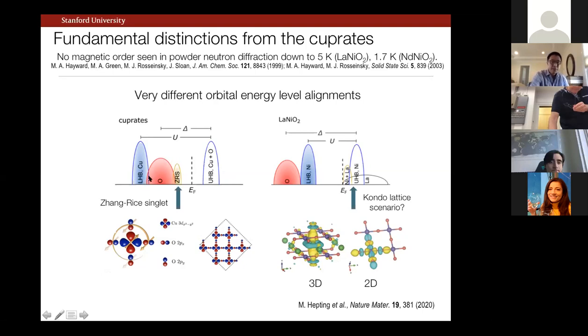The oxygen 2p band is lying around here, such that when you start to hole dope this system, you start to form states of this Zhang-Rice singlet character here. Namely, it's composed of the hybridization between the copper 3d x squared minus y squared and the oxygen 2p states. The notion is in this Zaanen-Sawatzky-Allen scheme that you're in this charge transfer regime. And so the hole is actually coming out of the oxygen ligand field, and it's making an overall singlet in the sense that these are now anti-aligned.